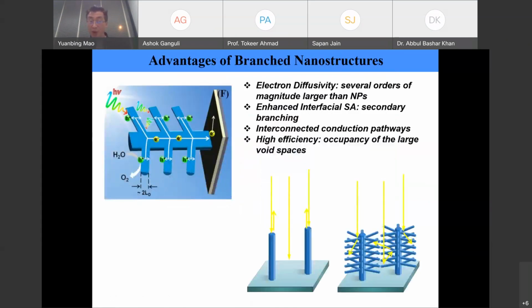So that's one aspect. If I want to summarize, there are several advantages of this type of 3-dimensional structure, right? The electron diffusivity is several orders of magnitude larger than in nanoparticles. Then there is the enhanced interfacial surface area because of those secondary branches, and the connected conduction pathways, right? Because in these 3-dimensional nanostructures, the charge carriers can move smoothly. It's just like a freeway instead of local streets. On a freeway there's no signal light, so we can go much faster. And there is also higher efficiency because the branches occupy the large void spaces. So those are the advantages.